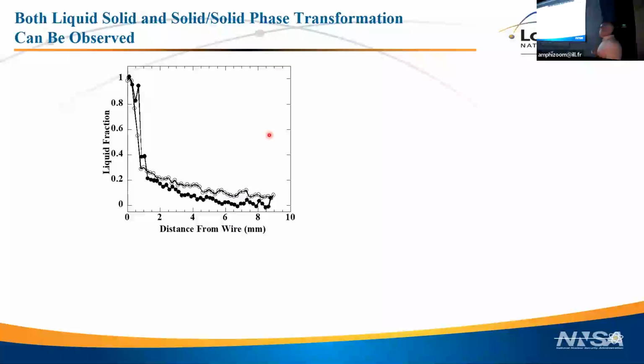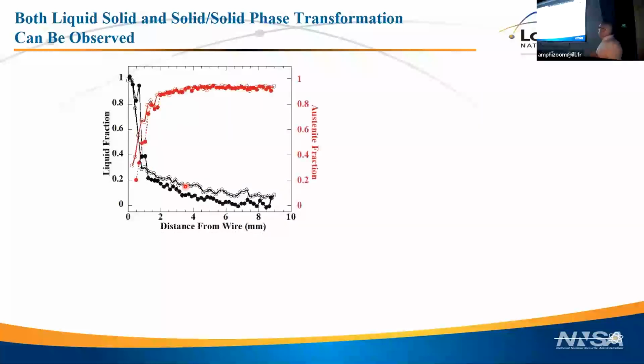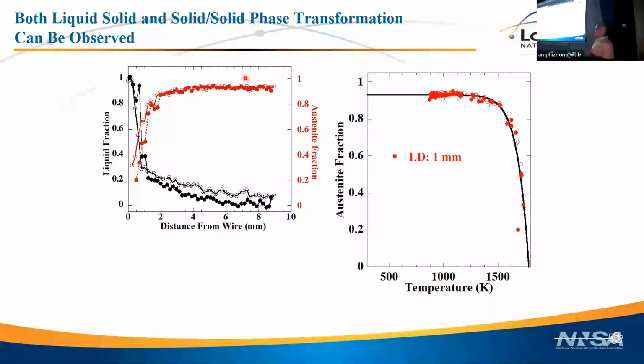We can pull out the liquid and solid volume fraction, and even now, we don't get very much of the changeover from liquid to solid. That really happens quickly. We do get the evolution at later time, and we actually do quite well looking at the austenite fraction. So the red line here is showing the solid-solid phase transformation as it goes from being, it should form as ferrite and then transform to austenite, and that's what this red line is showing. We can pull out the austenite fraction as a function of temperature now, so we can look at the rate of the transformation. So again, when it solidifies out here at high temperature, it's almost all ferrite, so there's essentially zero austenite, and then as it cools, you see the austenite starts to dominate, and it'll stop at about 95%.